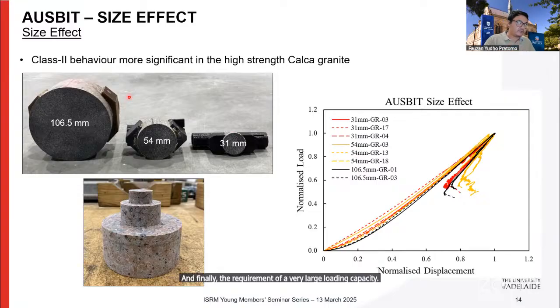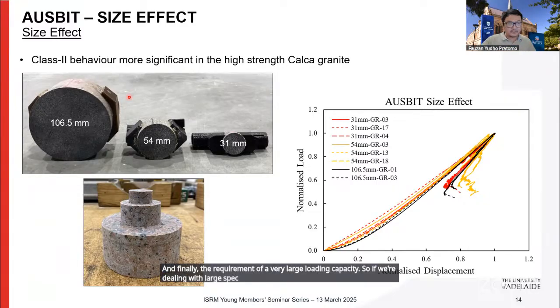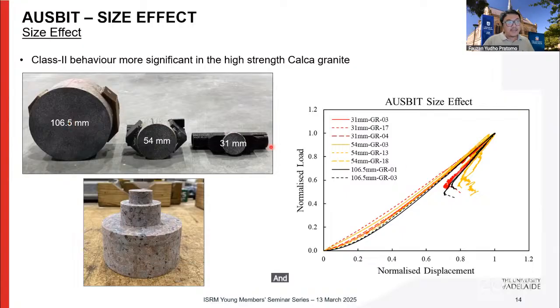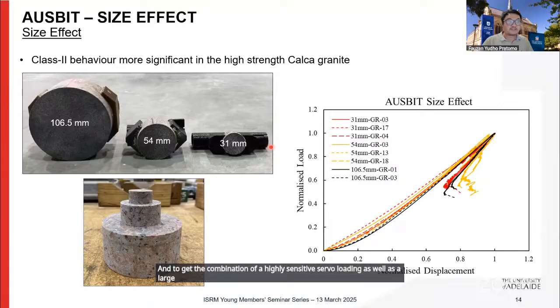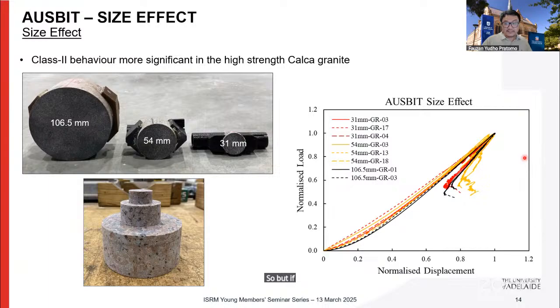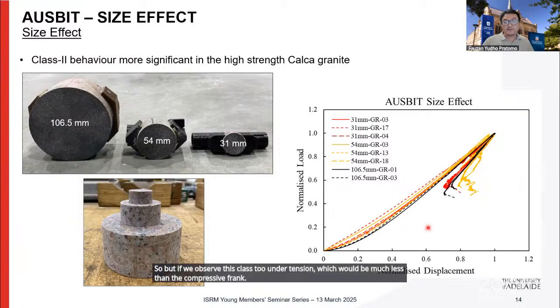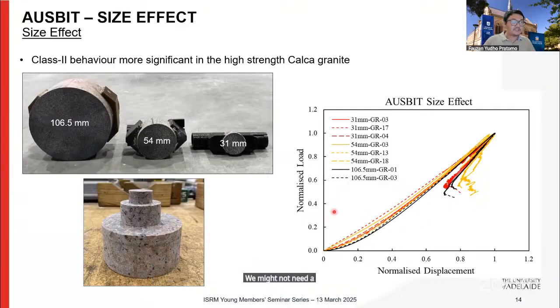So if we're dealing with large specimens of hard rocks, then we need a machine that could facilitate the need of those large loads. And to get the combination of a highly sensitive servo loading as well as a large loading capacity can be very expensive. But if we observe this class 2 under tension, which would be much less than the compressive strength, we might not need a very large load capacity machine.